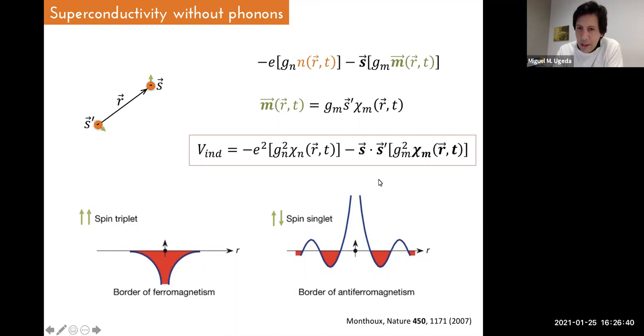In the case of antiferromagnetic interaction, this is also a minus sign, but it turns out that in this particular case, when the material is at the border of antiferromagnetism, the spin susceptibility is maximum and positive at the origin, but oscillates in space, more or less with the periodicity of the lattice constant. And that creates as well regions of attraction for two electrons in a spin singlet. So in other words, materials that are close to antiferromagnetism usually follow this way to couple electrons and form Cooper pairs. At the border of ferromagnetism, this attractive coupling is also possible in the form of a spin triplet configuration.